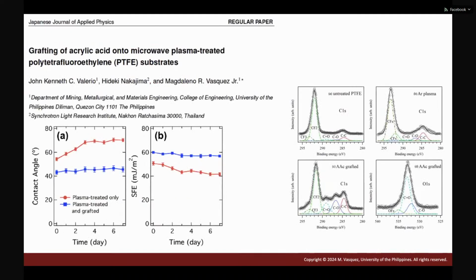So here's an example of our work on grafting acrylic acid on PTFE. In this graph, if you only treat your surface, then after 1 day, or within 24 hours, you will notice the hydrophobic recovery. And over time, after 7 days, you slightly increase the hydrophobic nature of your surface. Now, unlike that, for plasma-treated and grafted PTFE, as you can see here, the contact angle is almost constant, or the surface energy here is almost constant. So we're able to show that there was grafting of acrylic acid on the surface. One application of this is really for biomaterials.